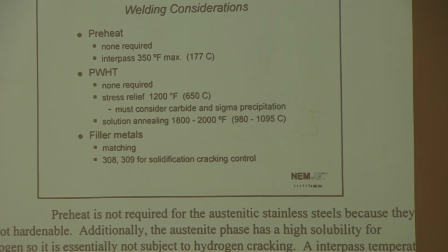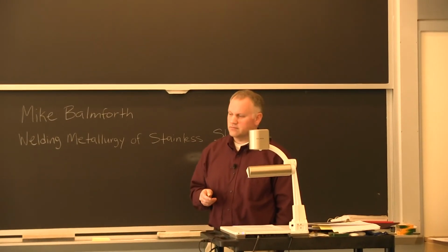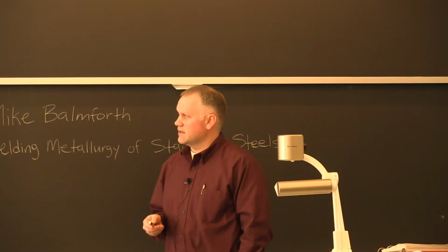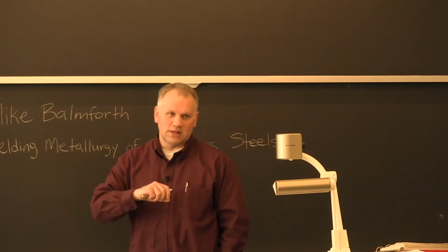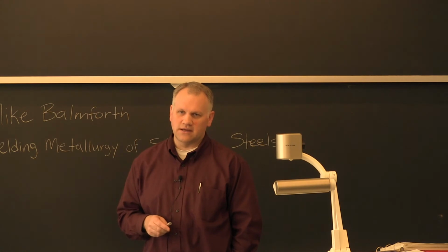It's very important with stainless steels that you weld in an inert environment, because at high temperatures the chromium oxides form very rapidly, and you get what's called sugaring. You get this black oxide all over everything.